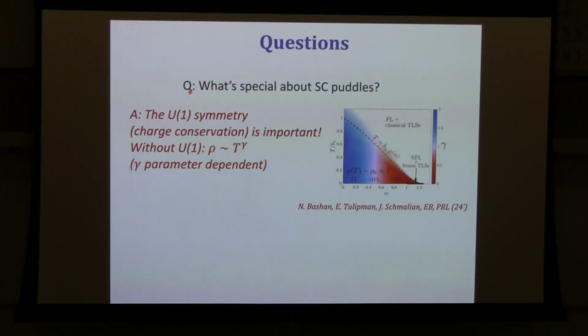And of course, the devil's in the details. You have to do the full analysis. One question that we wanted to address is what is actually special about superconducting puddles as opposed to some other impurity, like a charge impurity or a spin impurity? If you try to replace the superconducting puddles by some other localized degree of freedom that can scatter electrons, can the same mechanism work? And it turns out that no, there's something very special about these superconducting puddles. There's a U(1) symmetry in the problem, which just corresponds to the charge conservation in this Andreev process. And if you try to solve a similar problem of localized two-level systems interacting with electrons, you find that there is a strange metal phase, if you like, or a strange metal regime, but the scattering rate doesn't necessarily grow linearly with temperature.